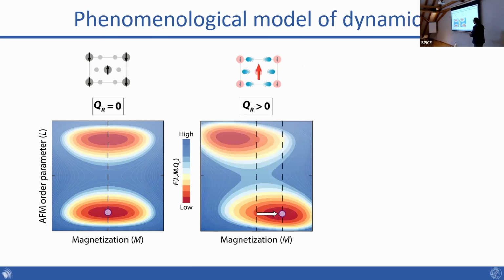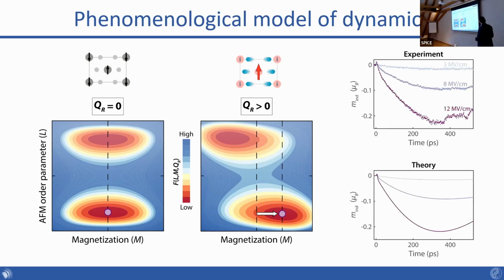And the picture that you end up with is something like this, where you have, in equilibrium, before you drive anything, the antiferromagnetic order parameter on this axis, the magnetization on this axis, and the color gives you the depth of the well. You have the two antiferromagnetic wells corresponding to the two domains of your Néel order vector. And in equilibrium, you have always that the magnetization is sitting at 0. And when you drive this QR mode, essentially what you're going to do is you kind of displace this free energy so that you end up with a net magnetization. This then goes back down very fast and ends up acting like kind of an impulsive excitation. Okay, and then if you write down and calculate what the dynamics would look like, here's the experiment, here's the theory for the different pulse electric fields, you get very good agreement. Okay, but this is just a very simple model.